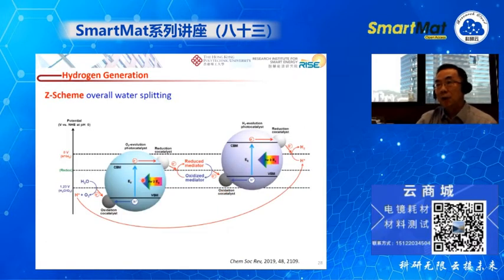And sometimes, if the conduction band of one material is not enough to generate the hydrogen, and if the valence band of another material is not suitable for the oxygen production, people can use a so-called Z-scheme strategy to add a redox mediator to combine these two materials together, and it can effectively transfer the electron from the conduction band of this material to the hole of the valence band of another one.